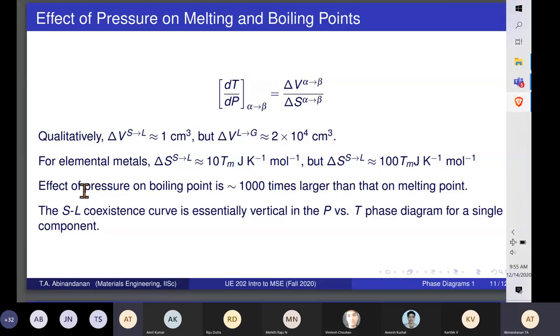So the bottom line is that the effect of pressure on boiling point is at least 1,000 times larger than the effect of pressure on the melting point. The factor of 1,000 comes because you have this factor of 10,000 here and a factor of 10 here, and so putting them together, you get this really huge factor. More importantly, the melting curve in the phase diagram is essentially vertical when you look at it in the P versus T phase diagram, P on the y-axis and T on the x-axis, for a single component.